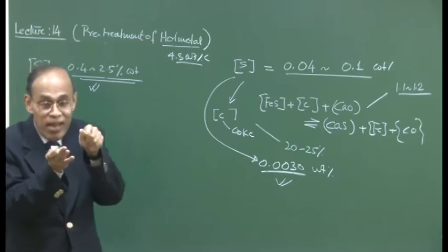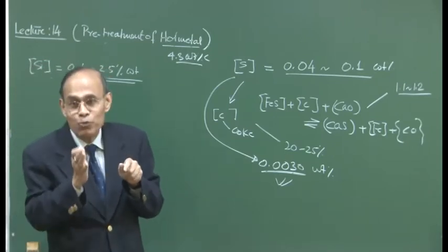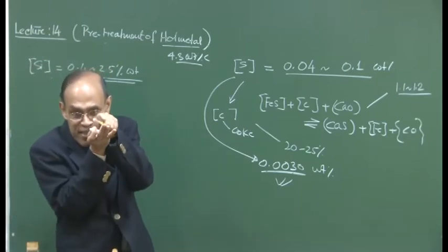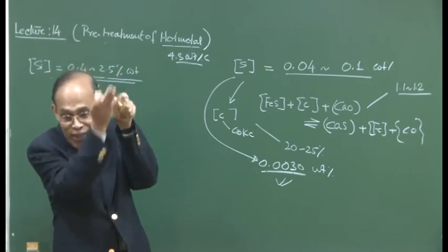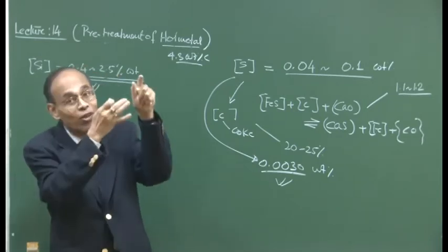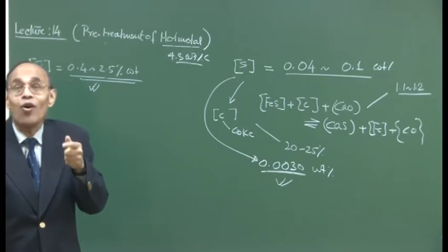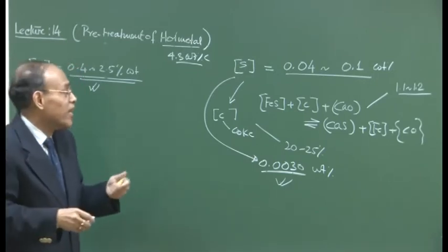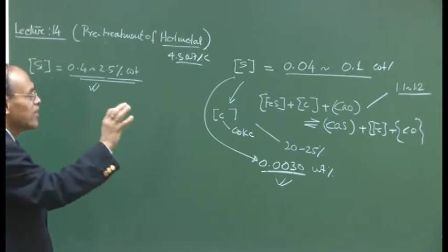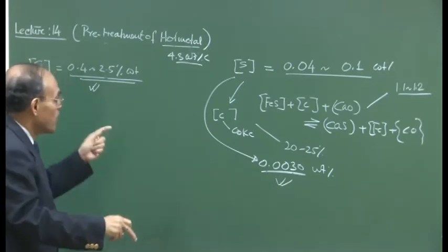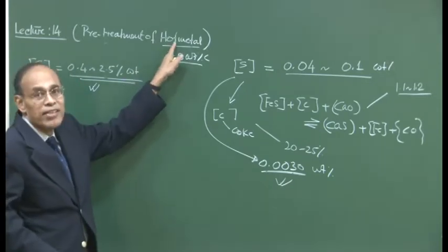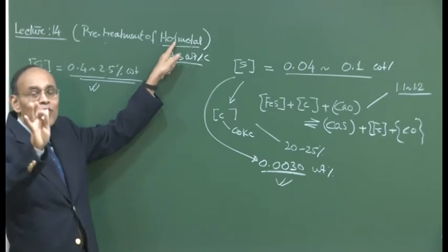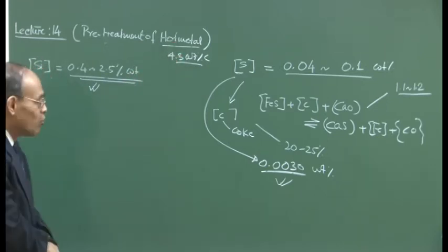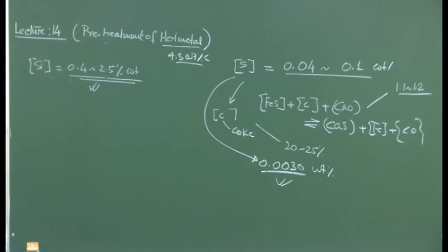So, I said the iron iron oxide line and phosphorus phosphorus pentoxide line in the Ellingham diagram are extremely close. So, if all the iron is reduced, it essentially implies all the phosphorus is reduced as well, and all reduced elements go to the metal phase, as a result of which phosphorus present in the charge is totally reduced in the iron blast furnace and finally lands up in the hot metal itself. That poses no problem, because steel making is a site for phosphorus elimination.